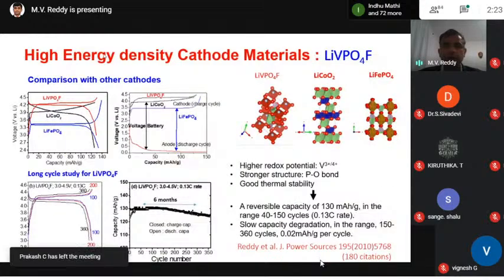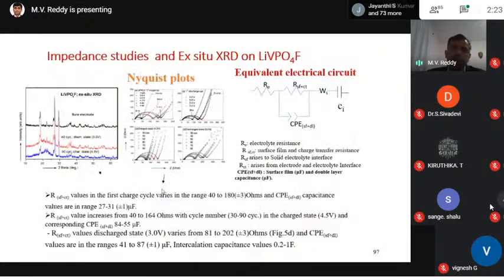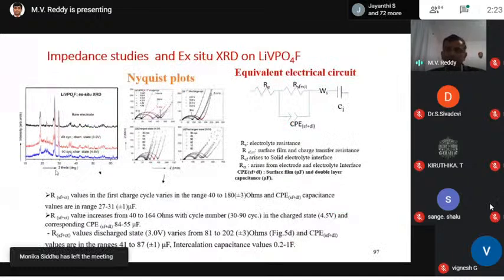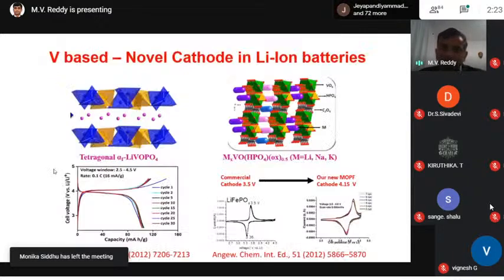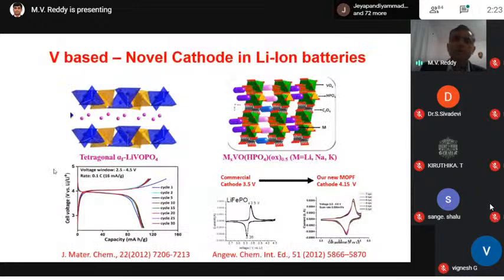We can do, for example, charge discharge cycling. So the typical example of lithium vanadium fluorophosphate is the charge and discharge potentials. As you can see, nearly 6 months we ran the material and it has reasonably good cycling stability. We also checked with impedance studies, as well as the cycled electrode, which clearly show that this material seems to be stable. So another example is the novel vanadium based materials.